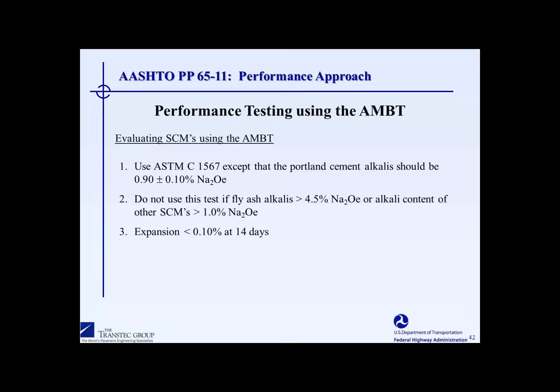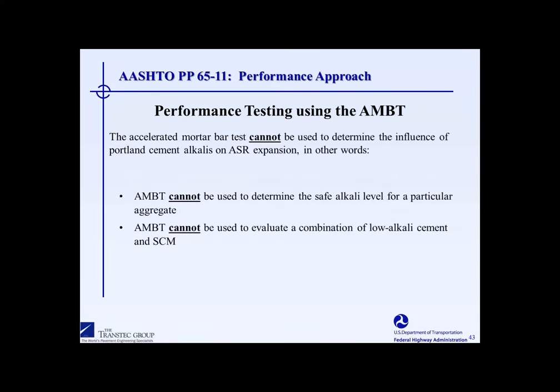With regard to the accelerated mortar bar test, as I said, provided that you can establish a correlation between AASHTO T303 and the concrete prism test, one can then go forward and use the accelerated mortar bar test for evaluating SCMs. What you'll see here is that we don't allow for the use of high alkali SCMs, because we're not able to really evaluate the contribution of the alkalis coming from the fly ash, because we're essentially putting these mortar bars in an infinite supply of alkalis in terms of the host solution. We recommend a 0.1% expansion limit at 14 days.